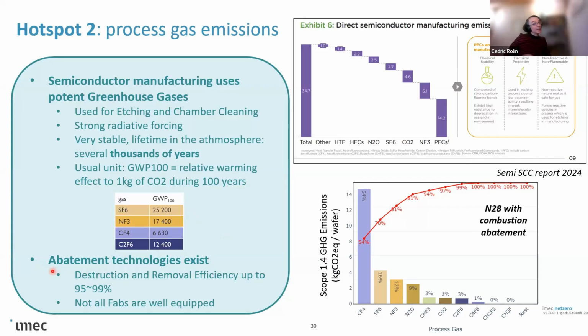So there are technologies that exist and that are deployed in the fabs to destroy those gases before they are being emitted. And they have typically a DRE, destruction removal efficiency, of up to 95 to 99%. And not all fabs are well equipped, in the sense that the older fabs that have been installed or fabricated before the year 2010 or even older are not necessarily well equipped with abatement technologies. And here this Pareto plot is showing from our modeling exercise what are the biggest emissions, and those are final emissions after abatement for the N28 nanometer example, where you can see that the most climate change is actually caused by the CF4 gas, followed by SF6, followed by this series of gases.